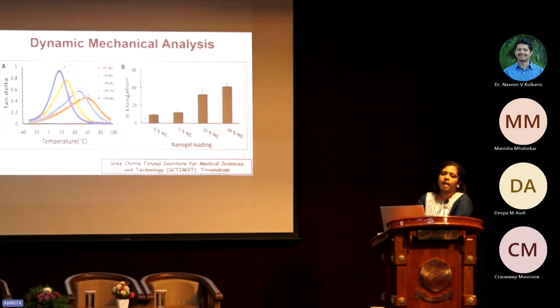and you can see that the tan delta value of the parent polymer matrix, that's the Exothane, is around 62 degrees Celsius, while when we incorporated the nanogel into the polymer matrix at different weight ratios, the Tg is also decreasing. For example, at 5 weight percentage of nanogel, the Tg value reduced to 47, and at 30 percentage nanogel content, it even reduced to 19 degrees Celsius. So that is very good, because at room temperature the material is very flexible, so it will be suitable for applications like blood bag or adhesives or soft liners, etc.